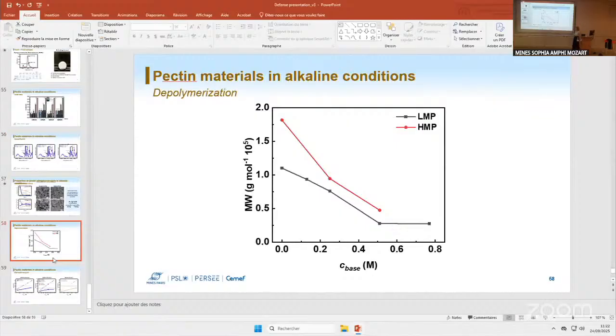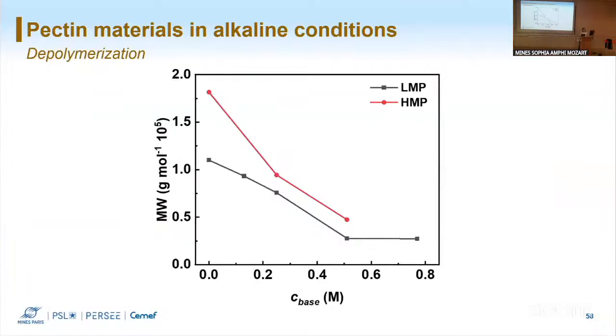No, probably not. Degree of esterification, you remove your esters, so they don't matter anymore in alkaline solution, right? And what about the charge effect in alkaline solution? The charge effect for the pectin chains. Yeah. In general, from the literature, when you increase the charge, you are supposed to have repulsion of the chains and then reduction of the viscosity of the solution. And this we see, up to pH 12.5, 13. And then suddenly we have something going on there.